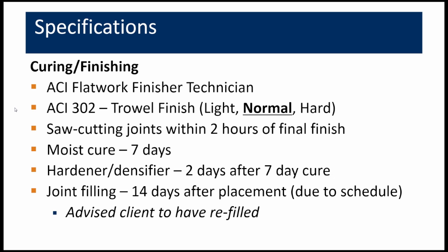We wanted saw cutting of the joints done within 2 hours of the final finish. We specified a 7-day moisture cure. 2 days after the cure, we installed a hardener and densifier, which is a liquid silicate material that reacts with the calcium hydroxide in the concrete to fill and densify those areas at the top surface of the slab. That has to be applied after hydration of the concrete so that the calcium hydroxide already exists. Due to the scheduling and working with the facility, the longest we could wait to delay joint filling was only 14 days. That's not ideal considering that more strength in the slab would be expected, but we advised the client to have those refilled at a later date.